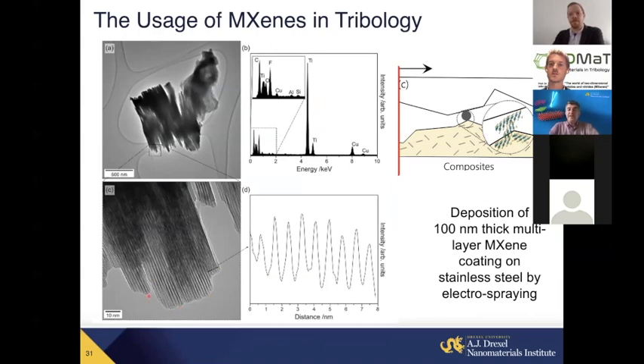And you can do it with nitrogen. You can do it with argon. You can do it with CO2. But you'll always get only this outer surface, unless you have completely exfoliated flakes and you make an aerogel in which you just measure the surface. So it's only the outer surface, which means it doesn't matter. Unlike, say, porous carbon, you cannot get this information for MXene with BET. So BET is unfortunately much less useful for analysis of MXenes. Yeah. Thank you very much.